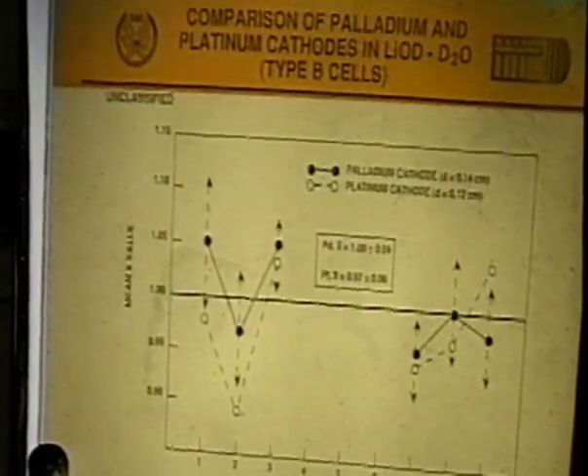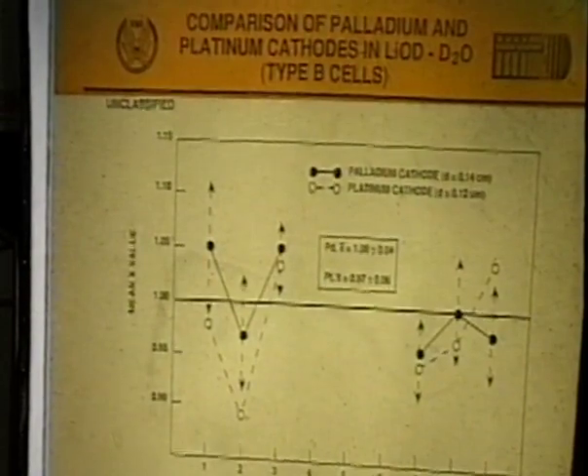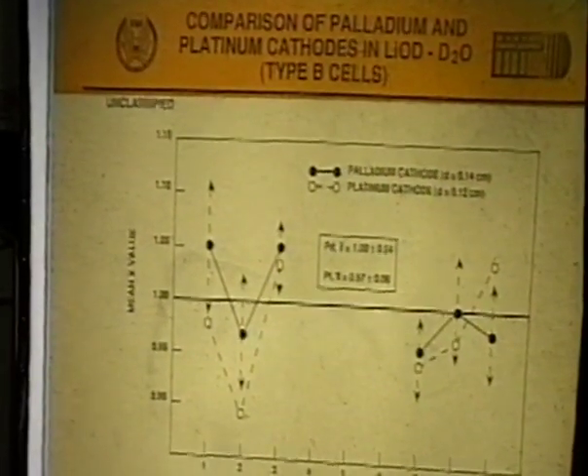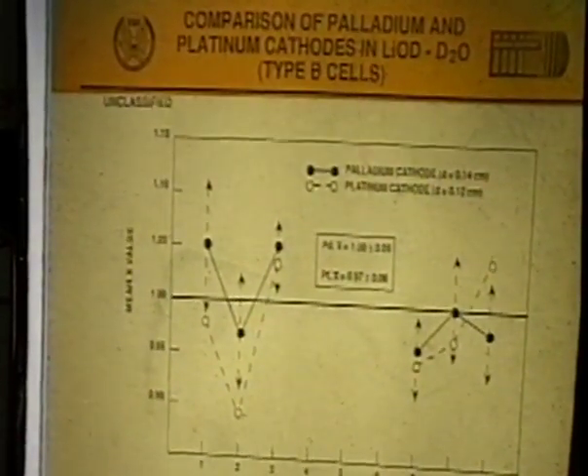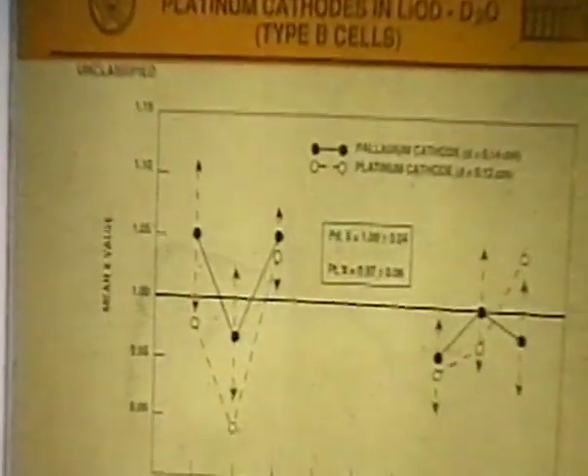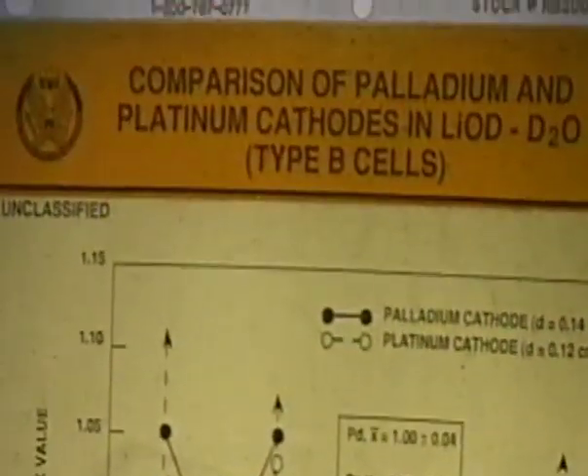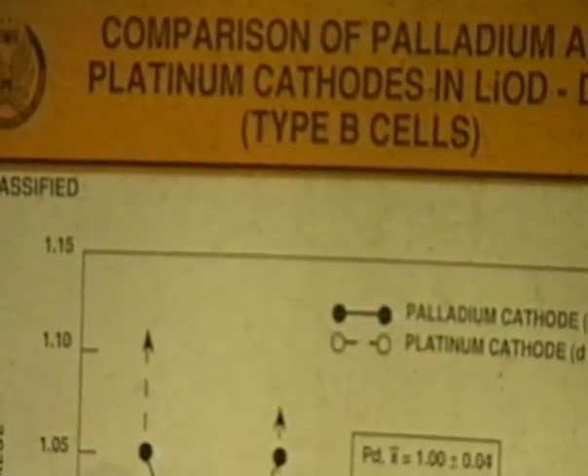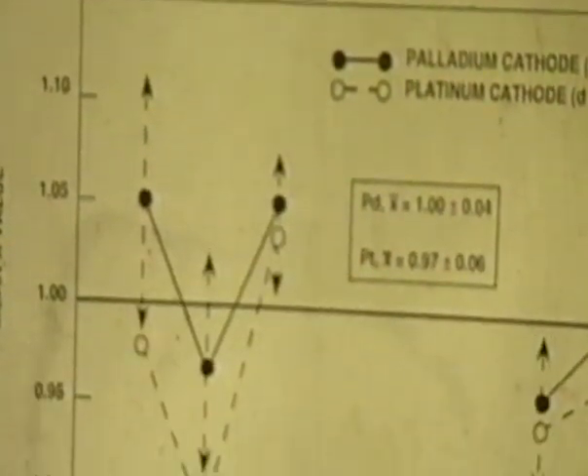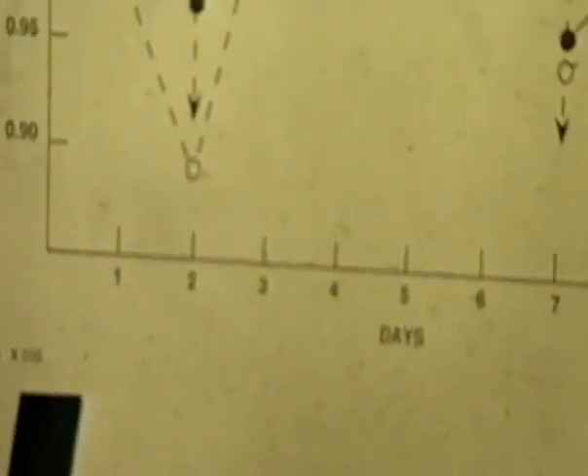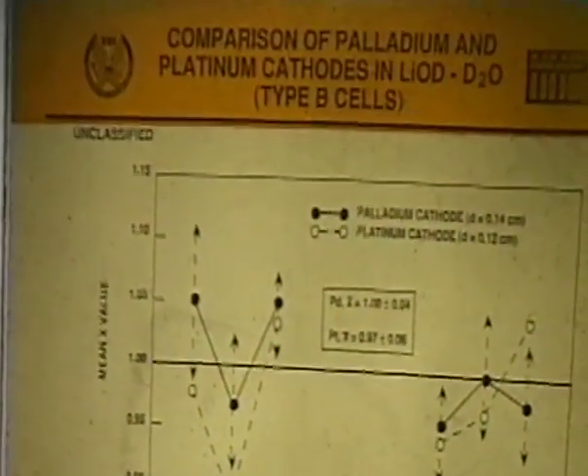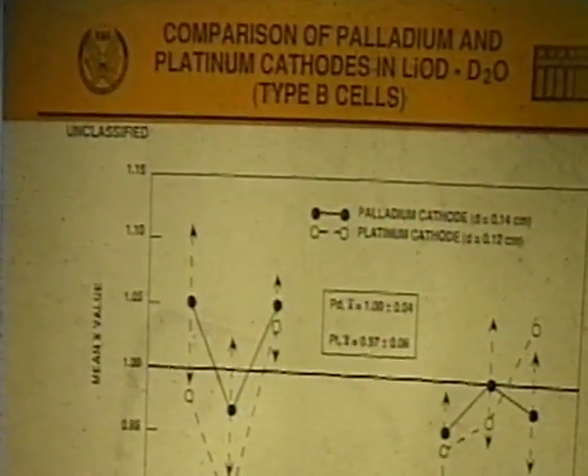In our first studies in 1989, for 5 months, we ran various experiments, probably about 6 experiments using palladium cathode that we just had on hand there from a company out of business, Wesco, I believe. And we compared it with a platinum cathode, and you can see that they both give about the same effect, and basically no excess heat for either palladium or platinum. And so that was one result that we reported and was published, that we had no excess heat.